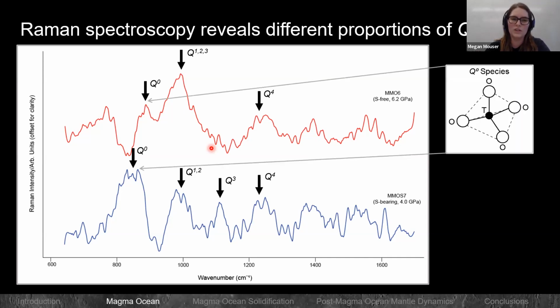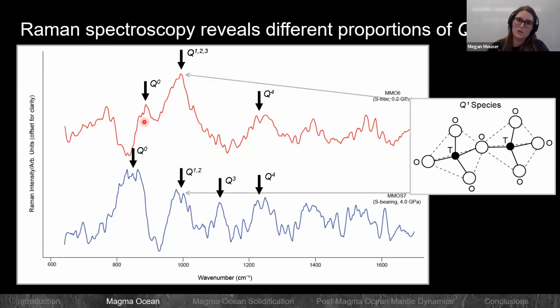But if we take a look at just the first peak, for example, the Q0, the isolated Q species, this peak is much more pronounced and defined within the sulfur-bearing liquid than it is in the sulfur-free. And if you move up to the next peak, where you are expected to have more polymerized species, this peak is much more pronounced within the sulfur-free than in the sulfur-bearing. So at least taking this analytical approach, we're able to confirm that the Q species and the polymerization within these liquids is different.